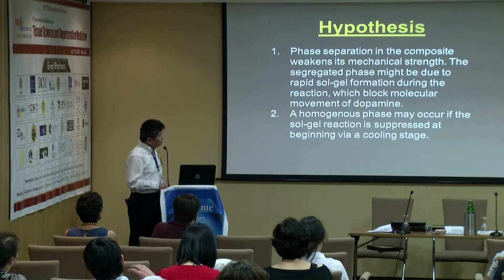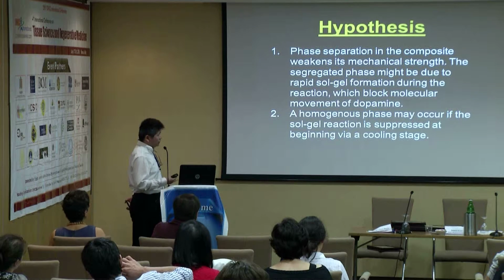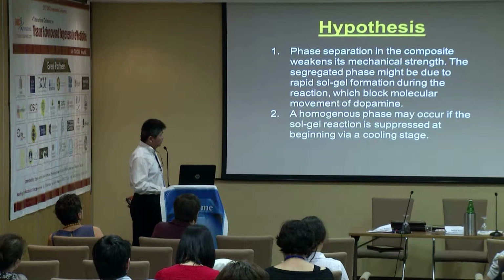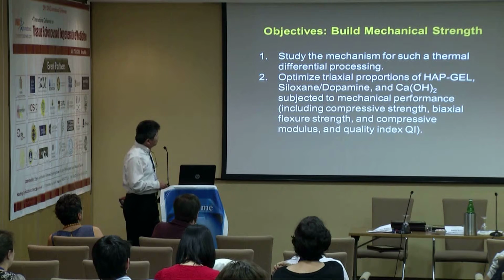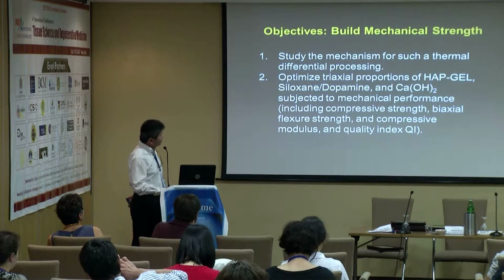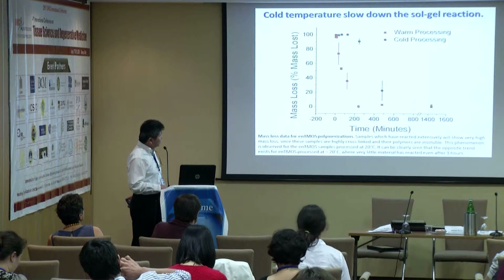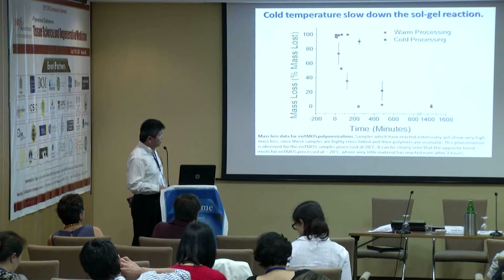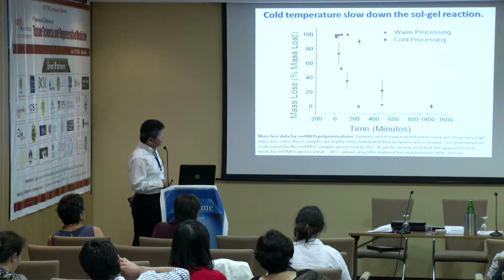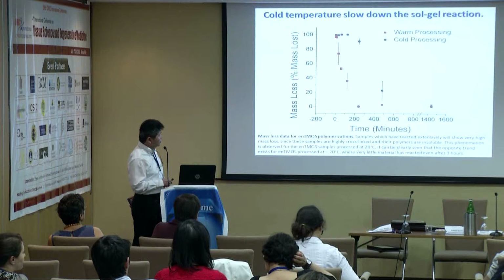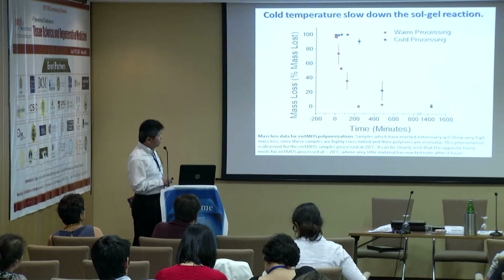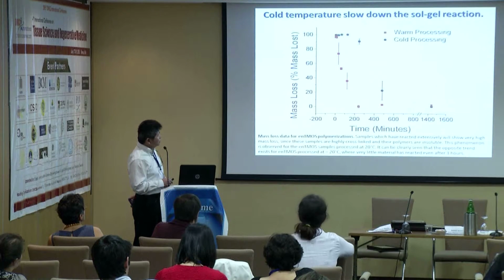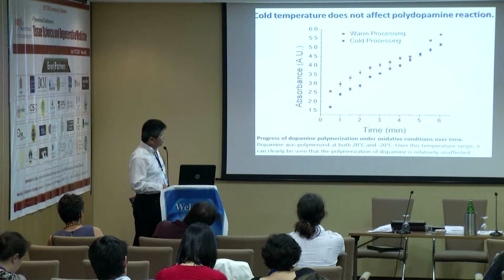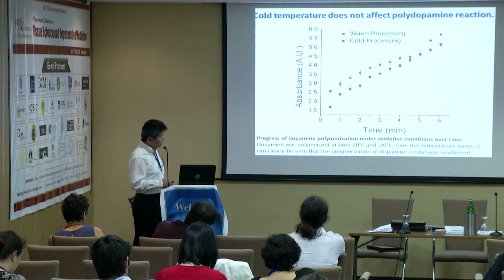And in this part, we make two hypotheses, just to make sure that using a differential temperature is helpful to the system, and also that the material is homogeneous. So by doing that, we ran some thermal processing. For example, in this case, we ran two different reactions, one at 20 degrees C, one at minus 20 degrees C, to look at the sol-gel reactions. Basically you can see that at a warm temperature, the sol-gel reaction goes very fast, within a few minutes. Under the cold reaction, the sol-gel reaction was suppressed, so it becomes very slow. On the other hand, when we look at the polydopamine reactions at 20 degrees versus minus 20 degrees, there's almost not much difference in terms of reaction trends.